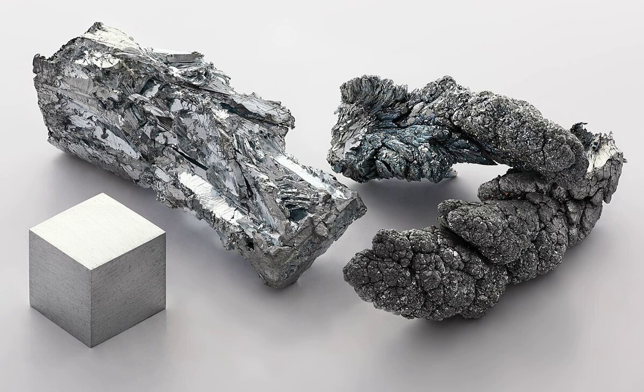Zinc metal is produced using extractive metallurgy. After grinding the ore, froth flotation, which selectively separates minerals from gangue by taking advantage of differences in their hydrophobicity, is used to get an ore concentrate. A final concentration of zinc of about 50% is reached by this process, with the remainder of the concentrate being sulfur, 32%, iron, 13%, and silicon dioxide, 5%.